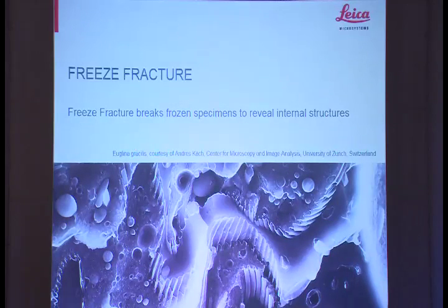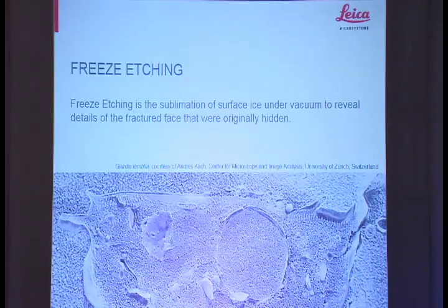Once coated, we get an image something like this, showing the membranes running through the cell. This is a euglena sample from one of our first beta tests. This instrument is brand new, so we just did some tests recently to show this technique. And this sample is frozen, and it's kept frozen and imaged frozen in the Cryo SEM. This sample has been freeze-etched, so in the SEM you can remove some water to reveal more detail.